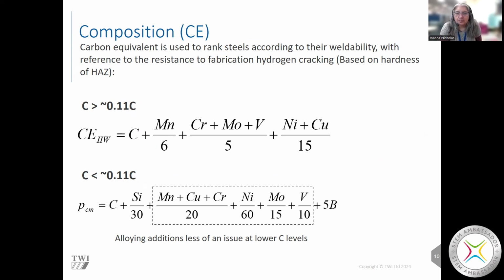So this carbon equivalent that I mentioned before is a shortcut to rank steels in line with their weldability, how easy it is to weld them, based on the hardness of the heat affected zone. There are two main ones: the IIW carbon equivalent, given at the top there, and the PCM, given at the bottom. In general, they all start with carbon, and then there are other elements included which give us a clue as to how hardenable something is. The key thing to note is that if the carbon is lower, the other elements matter a bit less. We would generally switch from the IIW carbon equivalent to the PCM if we're looking at lower carbon content steels. But those aren't the only carbon equivalents out there.